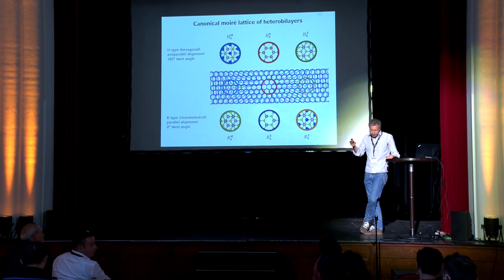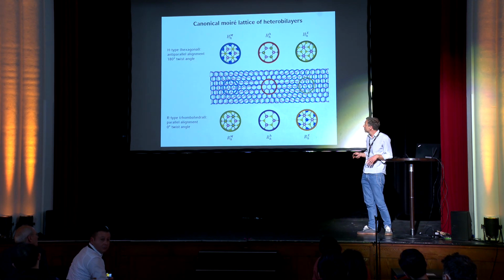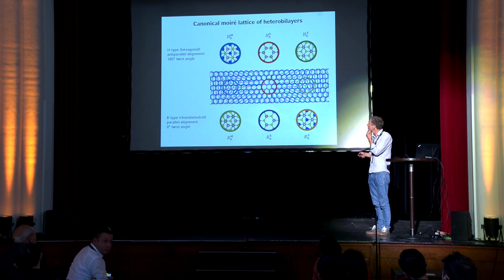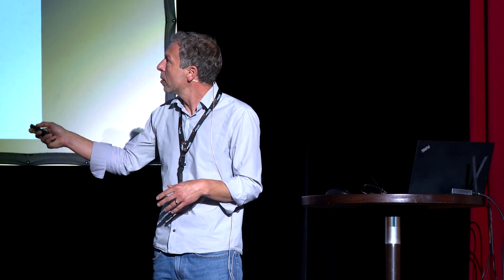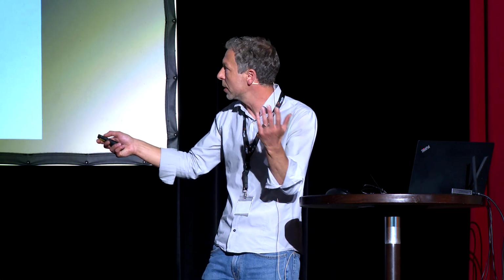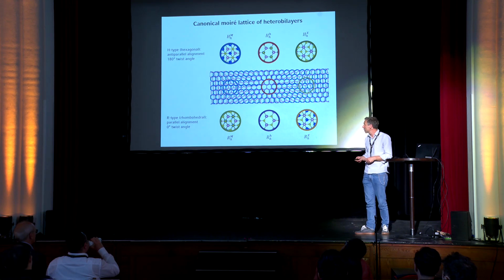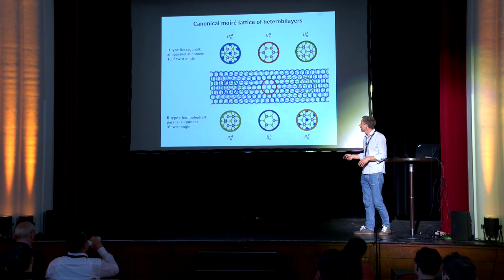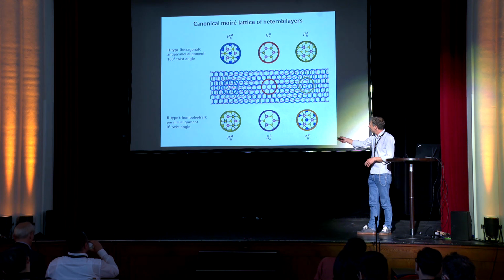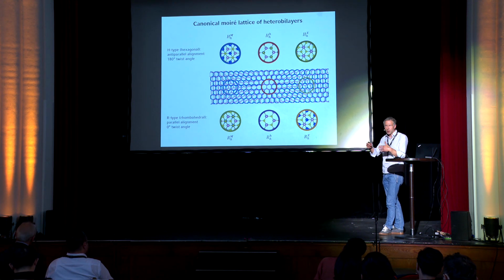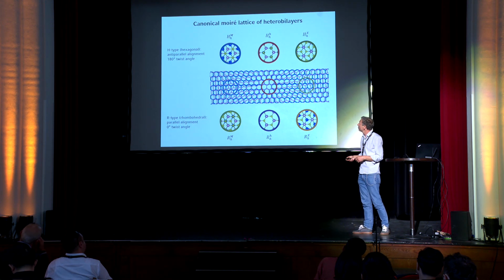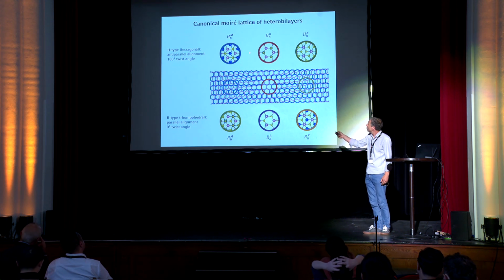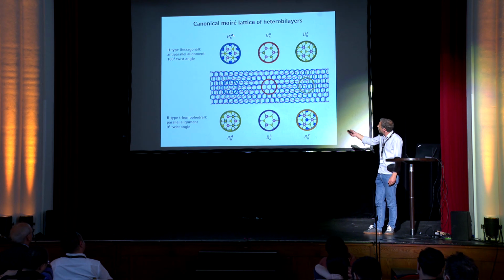So because TMDs or transition metal dichalcogenides monolayers lack an inversion center, we distinguish between H and R-type stacking. So H-type anti-parallel alignment or 60, 180 degree twist angle versus parallel alignment at or close to zero twist, right, comes along with a modulation throughout the moiré unit cell, and we see how we move through points of high symmetry atomic registries, labeled here according to the position of the metal over the center of the bottom hexagon.